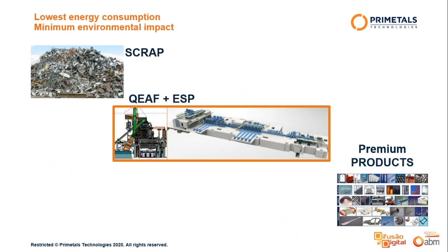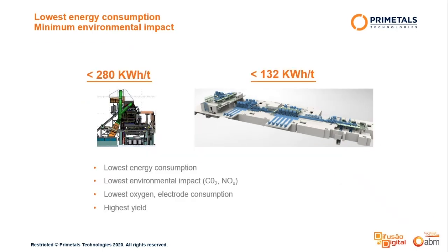In this context, it's also important to mention the possibility of coupling a Quantum EAF with an ESP line to a minimill for production of premium products from scrap. In this combination, the minimill melts the scrap on less than 280 kilowatt hours per ton in a Quantum furnace and rolls it to high quality on less than 132 kilowatt hours per ton in the ESP line. This means, besides lowest energy consumption, also lowest emissions and other consumptions at highest yield.